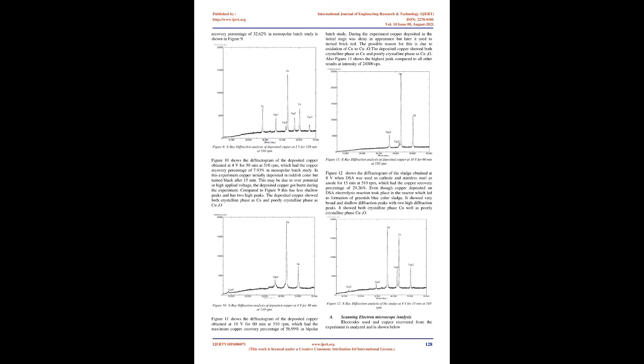Effect of agitation speed. To examine the effect of agitation speed on the amount of copper deposition, experiments were conducted at 2V for varying speeds of 50 rpm, 100 rpm, 300 rpm, and 500 rpm. As indicated in Figure 7, the amount of copper deposition increases with increase in agitation speed, reaching a maximum at 300 rpm. After reaching its maximum, it decreases with further increase in agitation speed.